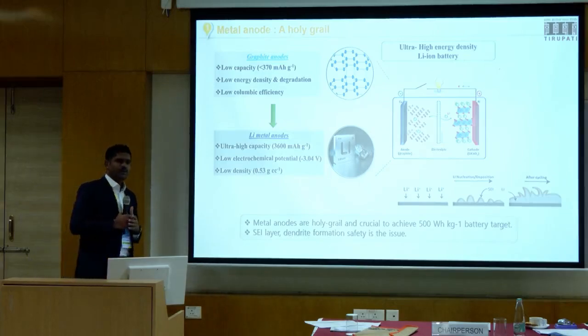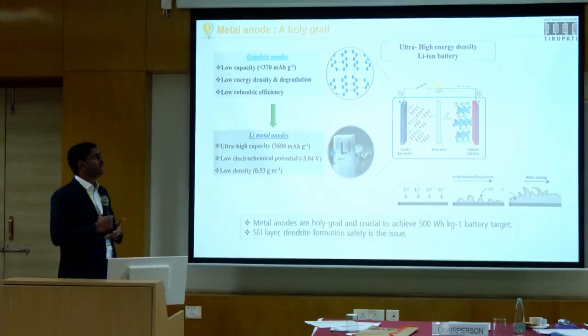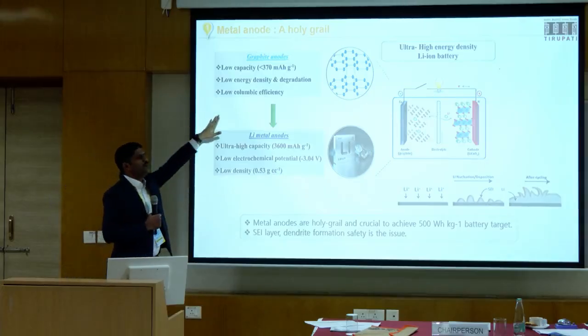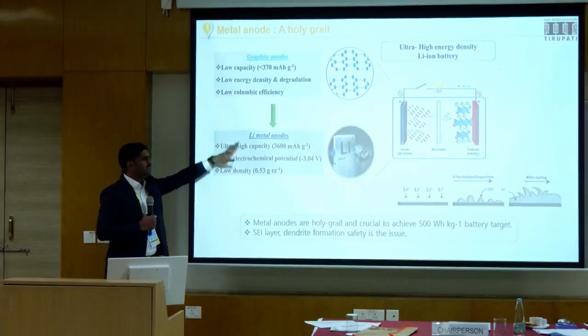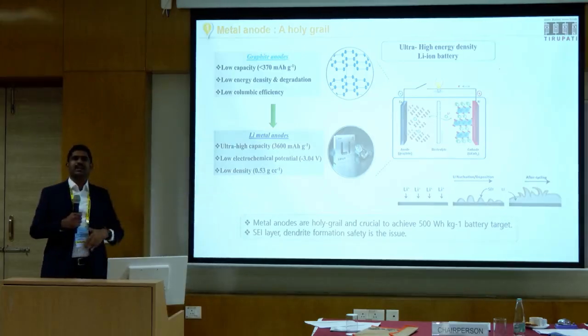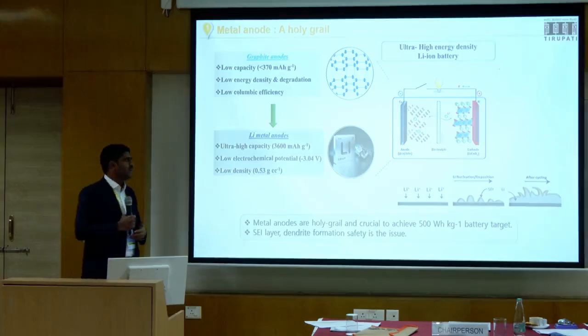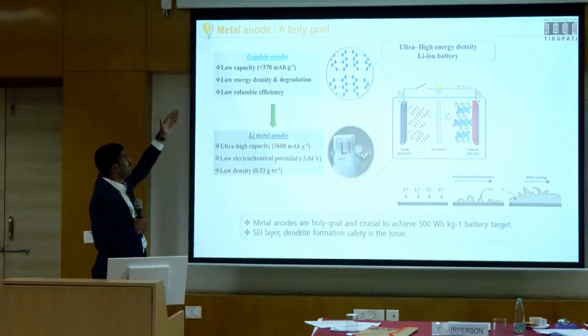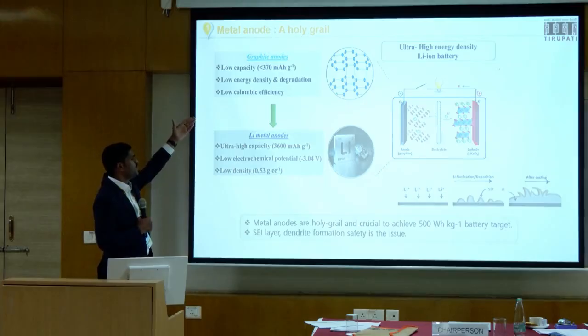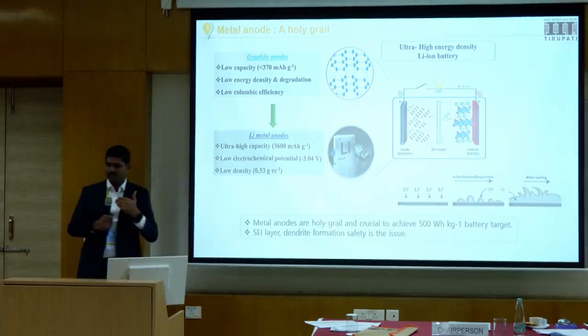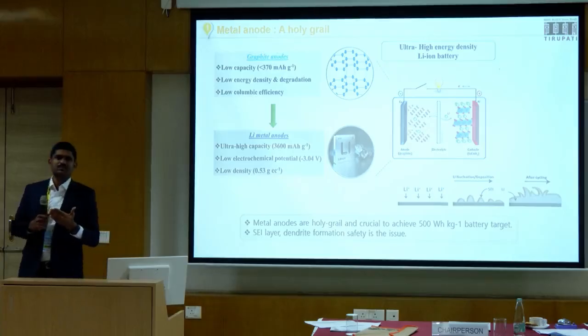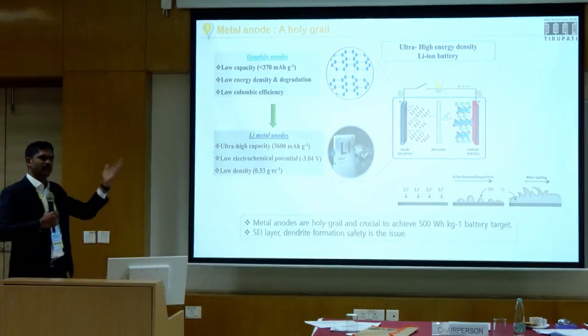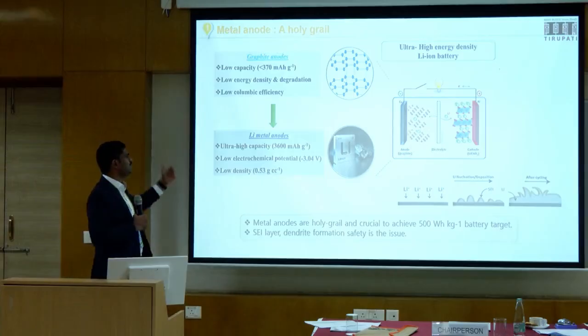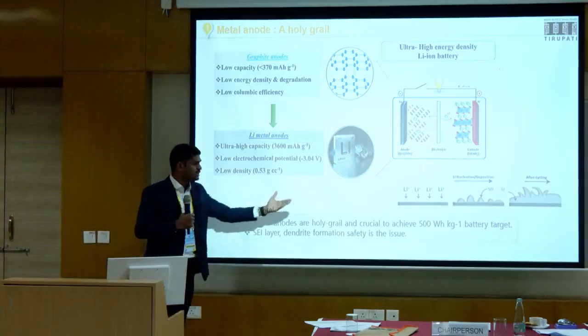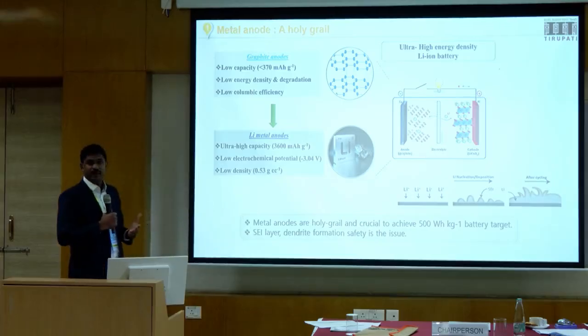And people, obviously a couple of years back, decided that with conventional graphite anodes, achieving that energy density is practically not possible. So they suggested moving from graphite based anodes to lithium metal anodes, moving back to a system which we used 30 or 40 years back. Moving to that system will really help us achieve an energy density of around 500 watt-hour per kilogram. That was their final observation.